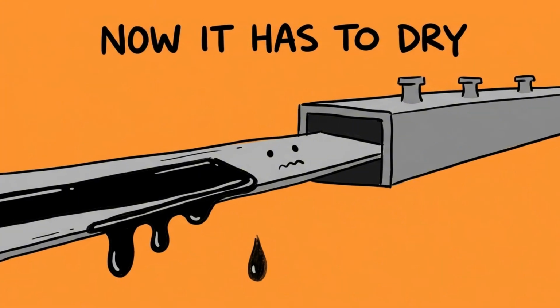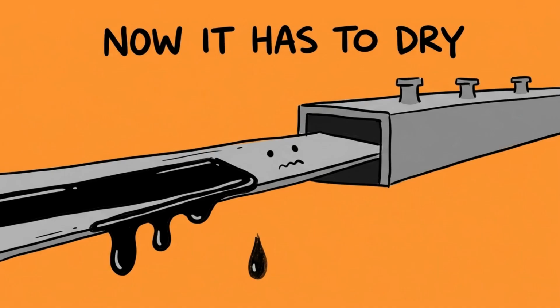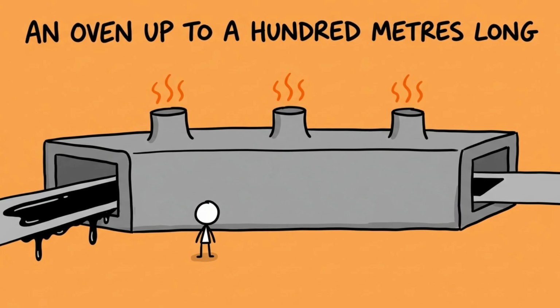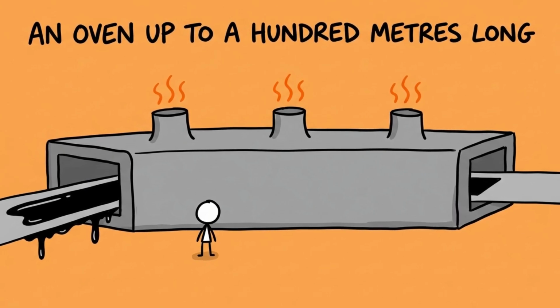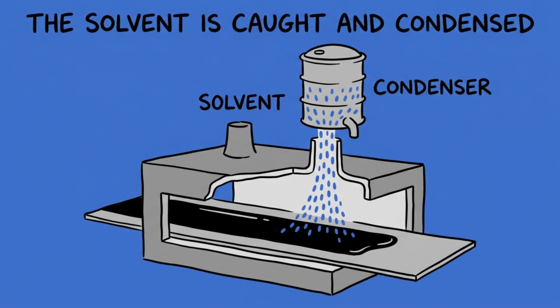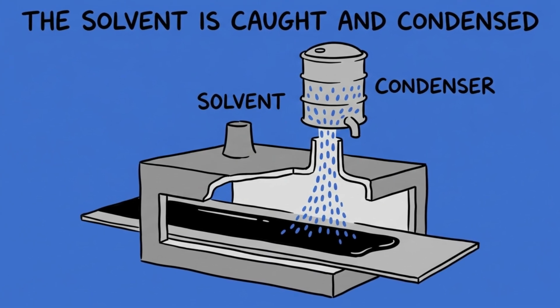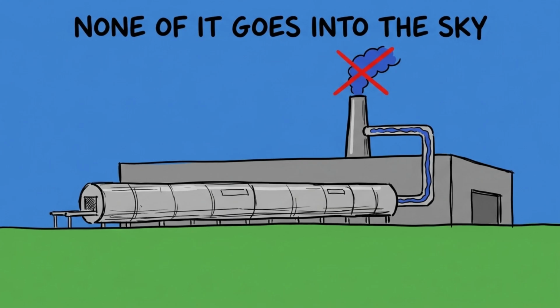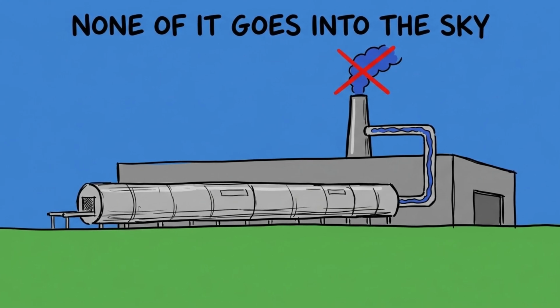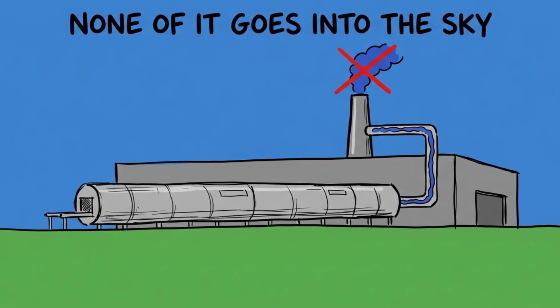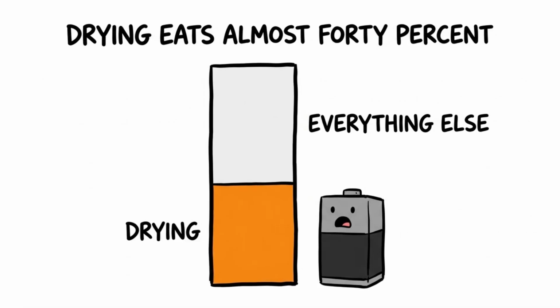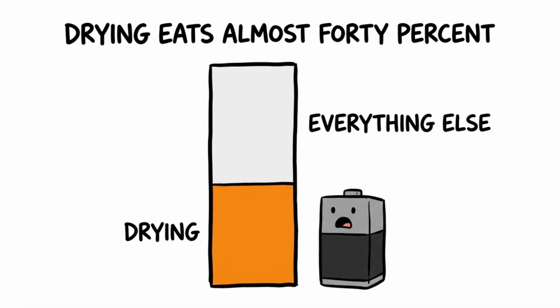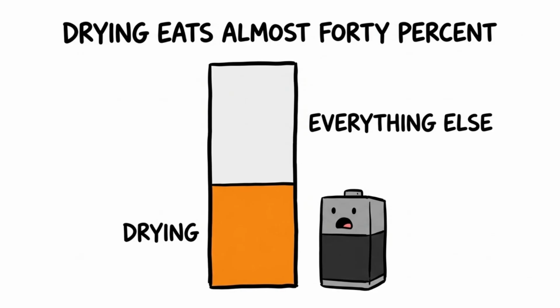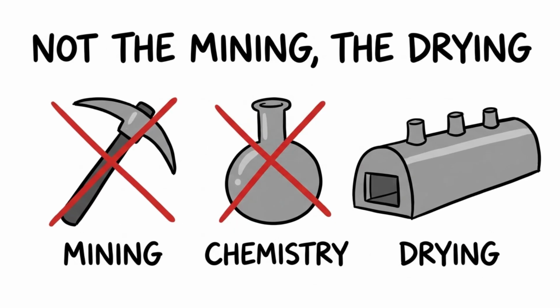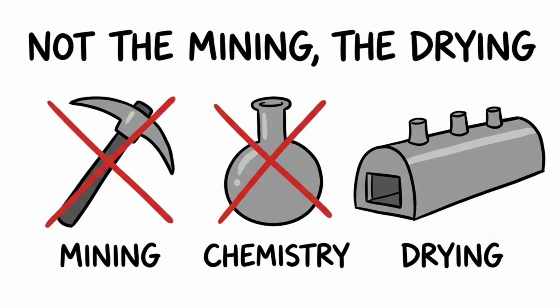Now the wet foil has to dry, and this is where the energy goes. The coated ribbon travels through a heated oven that can run up to 100 meters long. The solvent boils off and has to be captured, condensed, and reused, because it is expensive, and it is not something you vent into the sky. Drying and solvent recovery on their own can account for something close to 40% of the energy used to make the cell. Not the mining, not the chemistry, the drying.